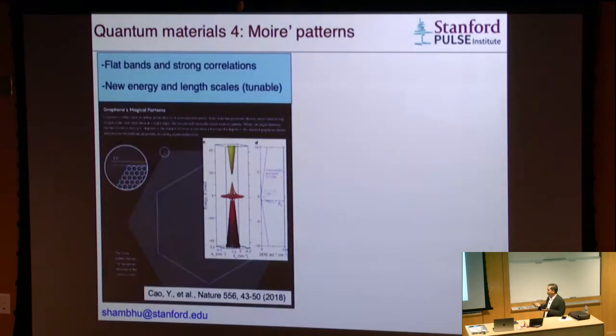Together with theorists here. So the Moiré lattice is one of the hot topics now in condensed matter physics, right? But it's also a really interesting optical crystal, I would say, and it could lead to a very interesting optical experiment. Maybe I should give another 1 minute on what the Moiré lattice is. So you have a graphene sheet, 2 graphene sheets. They are slightly misaligned, and when you do that, you give rise to a completely new periodicity that you see here in this big plot.